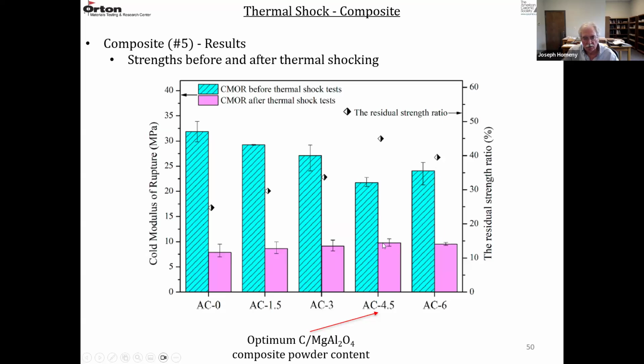But oddly enough, the residual strengths, the strengths after thermal shocking, go up with the carbon spinel powder additions. So they're a little bit better than these materials without the powder additions. And if you have a lower strength to start out with and a higher strength afterwards, the residual strength ratio goes up. So if you're looking at residual strength ratios, this material, AC 4.5, is what would be rated the best in terms of thermal shock. So any of these materials with the addition of the carbon spinel powders appear to have a better thermal shock resistance than without.